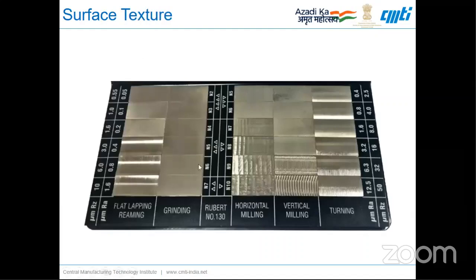The surface texture after these processes looks like this. Turning and milling roughness can be up to about 12.5 micron Ra. With turning we can achieve up to about 0.8, even 0.4 is possible. It again depends on machine dynamics and your tool condition, how sharp it is. With a grinding process we can achieve about 0.4 to 0.3 micrometer. With lapping we can achieve 50 nanometer, or 20 nanometer in some cases. And you cannot see the lay direction when it reaches less than 0.3 and 0.2